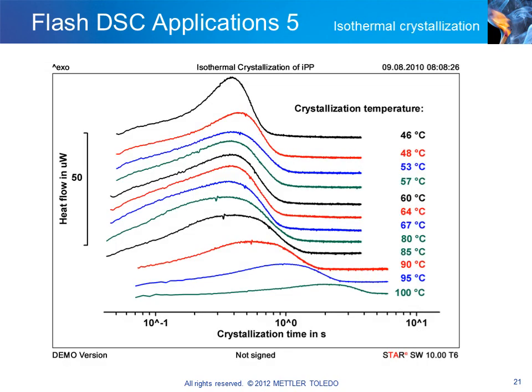Fast isothermal processes can also be measured with the Flash DSC-1. The slide shows some of the measurement curves obtained from the isothermal crystallization of isotactic polypropylene at crystallization temperatures between -10 and +110 degrees Celsius. The curves between 46 and 100 degrees illustrate how the peak maximum changes as a function of the isothermal crystallization temperature.